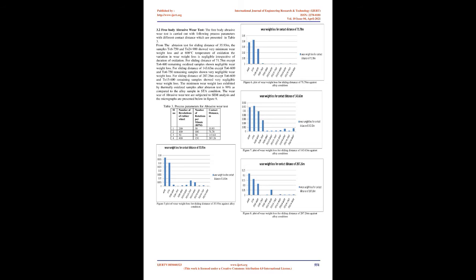The prepared specimen with the dimensions explained above is fixed in a tool holder with the hemispherical surface towards the rotating disc, and the wear test is carried out by bringing the hemispherical surface in contact with the rotating steel disc by adding weight as per the process parameters explained above for 20 minutes duration. After the wear test, the wear scar diameter of each sample is measured and the wear weight loss is estimated and presented in Table 2. The wear surfaces are studied in scanning electron microscope and the micrographs obtained are presented in Figure 4.